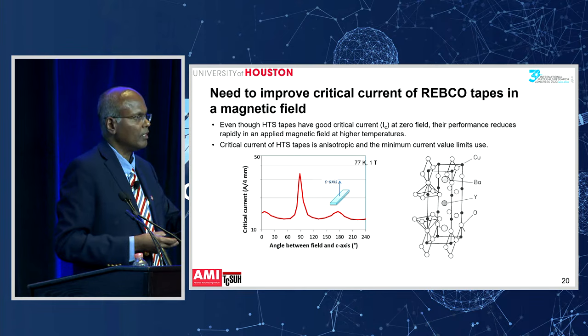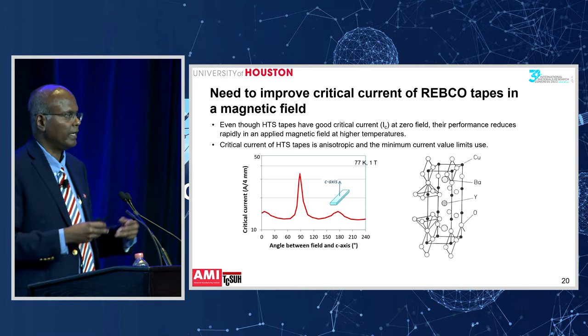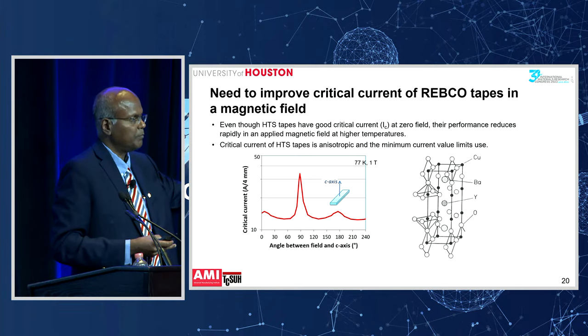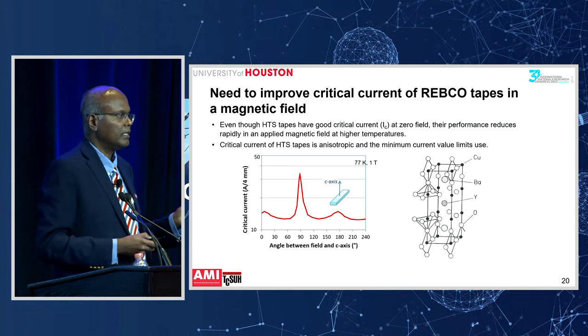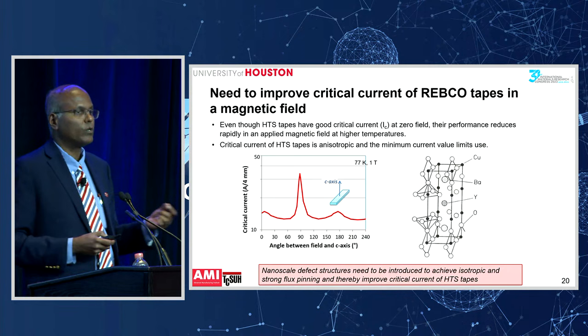And this is because the material is anisotropic. This is an orthorhombic material. It's very anisotropic. It has good conduction in the basal plane, but very poor conduction in the perpendicular direction. However, the good news is that the current density is not an intrinsic property. It's an extrinsic property, and that can be manipulated by adding nanoscale defects.